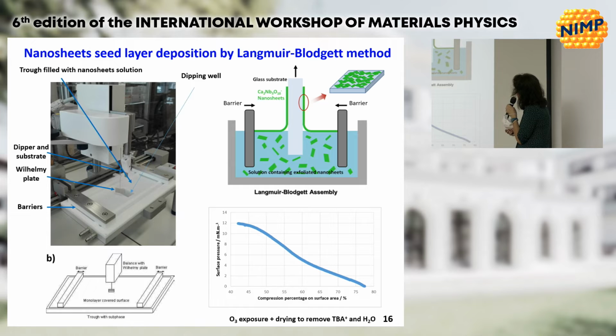And then we have these two barriers, which are moving together in this direction and pushing the nanosheets, which are at the interface between the liquid and the air, to transfer the material onto the substrate. So we measure the surface pressure of the liquid as a function of the compression percentage of the surface. And at some point, we decide to fix the surface pressure, just before this plateau. And this plateau corresponds to a very high coverage at the liquid-air interface. And then we move up the substrate, and the barriers manage to keep this value. So therefore, they are pushing the nanosheet layer onto the substrate.